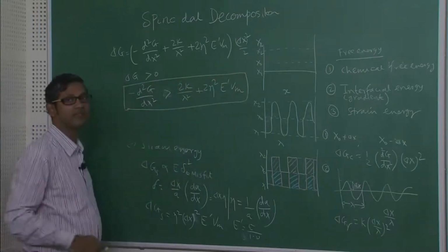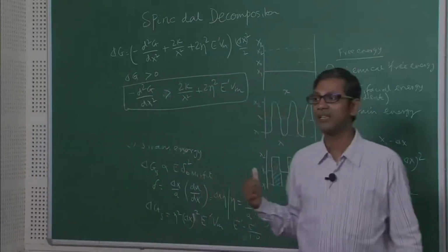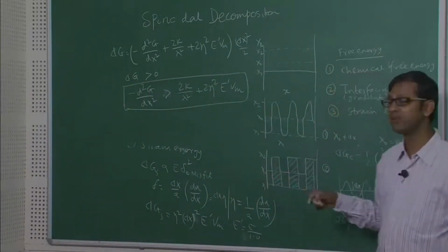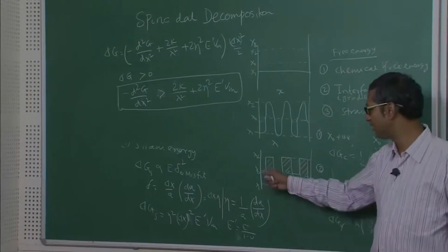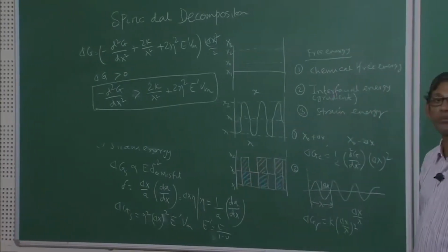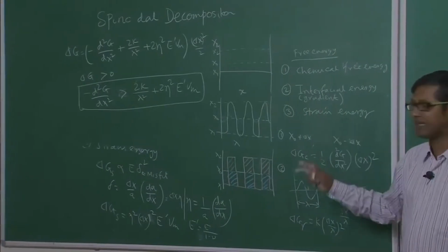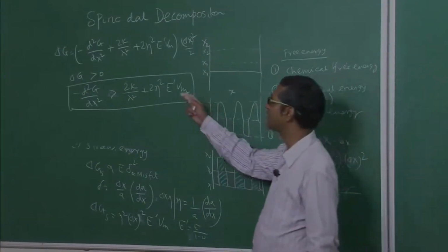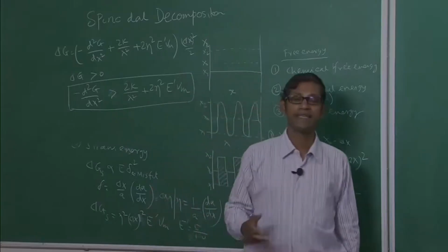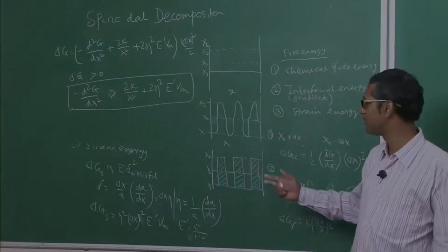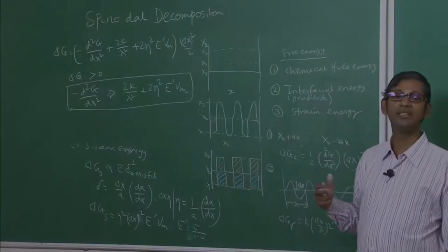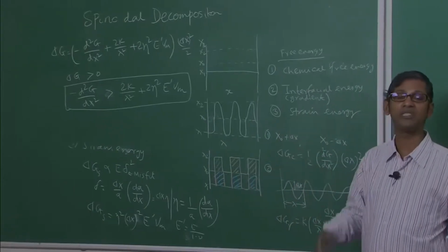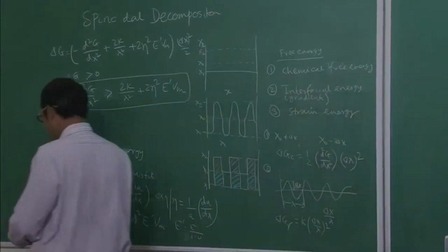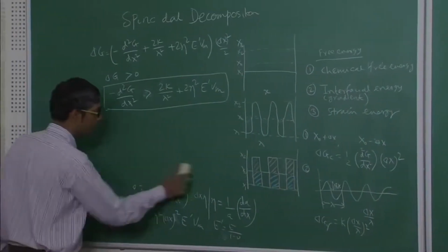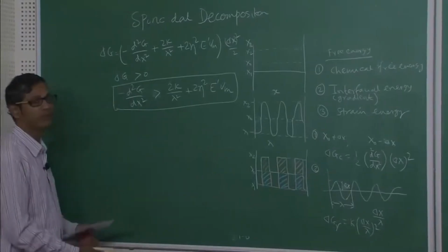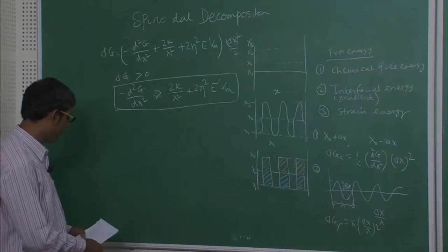This must be satisfied in a spinodal decomposition, this must be satisfied for it to be decomposing into this kind of compositionally rich and compositionally lean regions of particular component A or B. Please remember how this is derived, because this is very important, because this particular formalism is used in all kinds of simulation software which is basically used to calculate or generate the microstructure. Now it is very simple, because once we get the equation, it is very simple to calculate lambda. So therefore the limit is what?